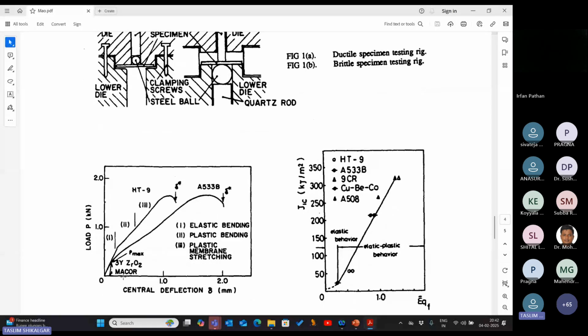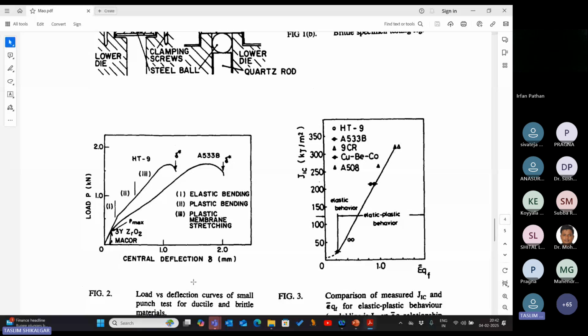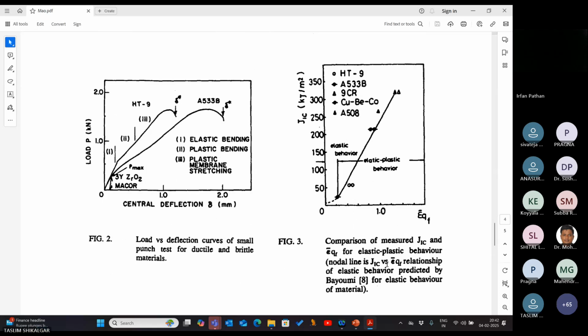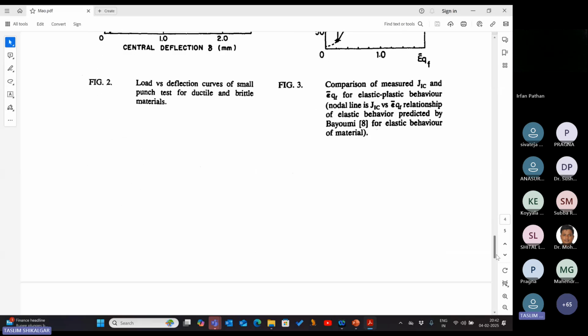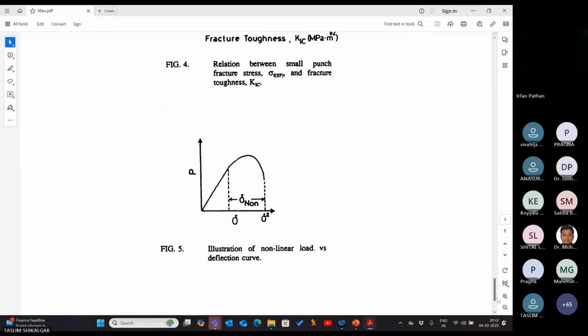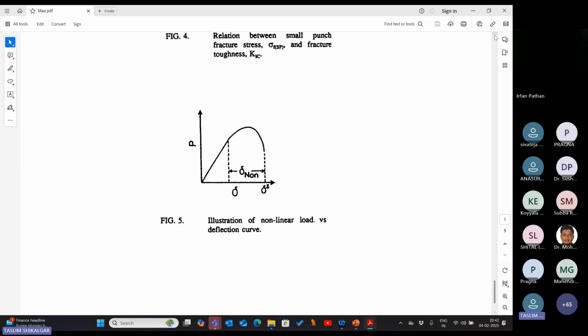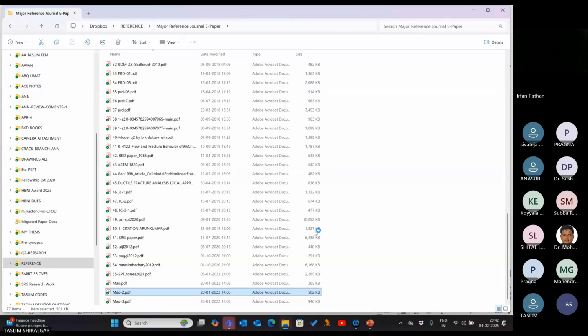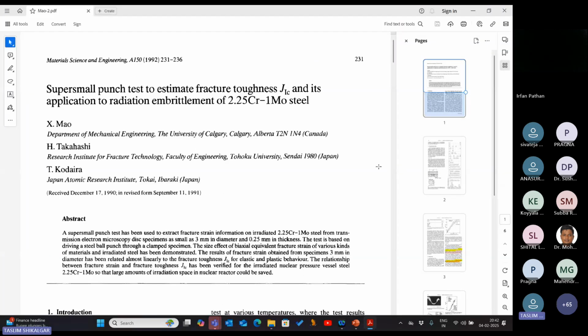He generated load versus central deflection, and with the help of this curve he calculated J1C as a function of the equivalent fracture strain. Sometimes it is called the biaxial fracture strain. So this journey started in 1991. This author published three papers regarding this SPT approach. He published a second paper in 1992.